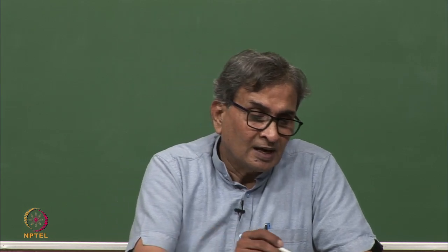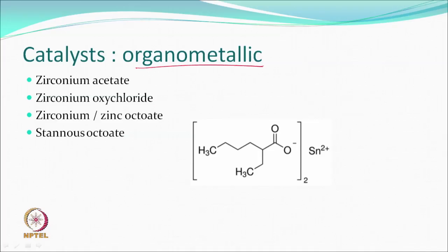The magic in some sense depends on organometallic catalysis. The catalysts which have been suggested, some of them are listed here: zirconium acetate or zirconium oxychloride or zinc octoate, zirconium octoate or stannous octoate. Stannous octoate is an example of this.